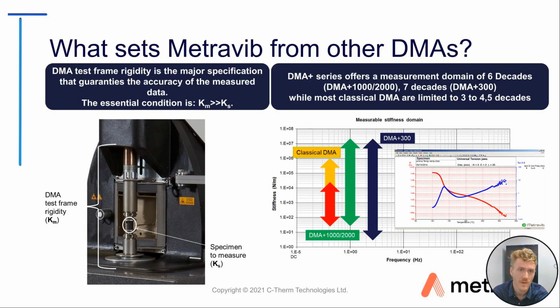So what sets Metravib apart from other DMAs? One thing is the rigidity of our test frame. The essential condition for performing DMA is that whatever you're measuring the sample with needs to be much stiffer than the sample itself. Because of this very stiff test frame, we're able to measure a large range of stiffnesses. The measurement domain is 6 decades on DMA Plus 1000 and 2000, and 7 decades on DMA Plus 300, whereas more classical DMAs are limited to around 3 to 5 decades of measurement.